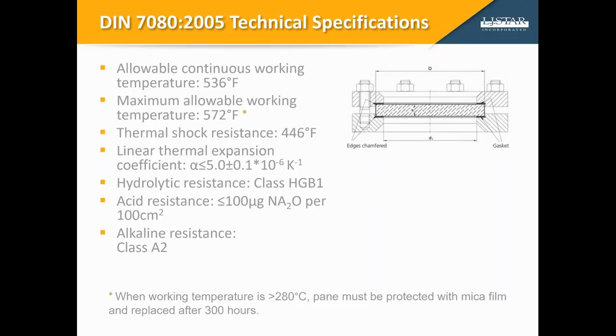The thermal shock resistance, ISO 718, is 446 degrees Fahrenheit. Hydrolytic resistance, ISO 719, is class HGB1. Borosilicate glass, having a very high hydrolytic resistance due to its composition, contains significant amounts of boric oxide. This test classifies glass resistance to chemical attack by heating the glass in contact with water. The acid resistance, according to ISO 1776, and the alkaline resistance, according to ISO 695, is shown in the slide, along with the linear thermal coefficient of expansion.